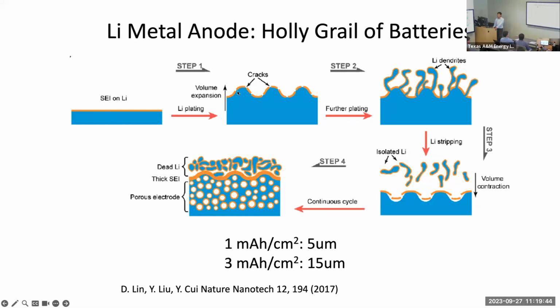Once you charge up the battery, you're going to plate the lithium, causing a thickness change. There's no guarantee it's layer by layer, very flat plating, because the surface curvature and topology change cause cracking of the solid electrolyte interface, the SEI. This crack is your hot spot. Lithium really likes to go in and deposit there fast. There's nothing to block that, right? You pick up the electron and deposit, and then you can form this metallic lithium dendrite. This dendrite can cause the battery to short and catch fire. So this is very bad.